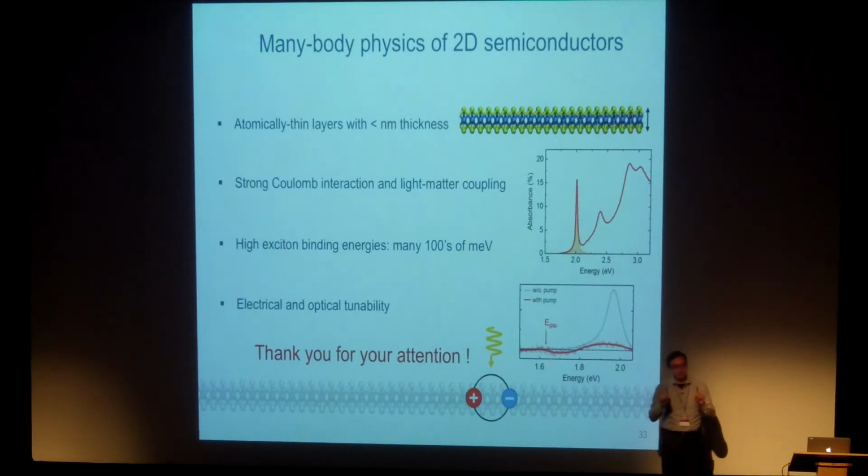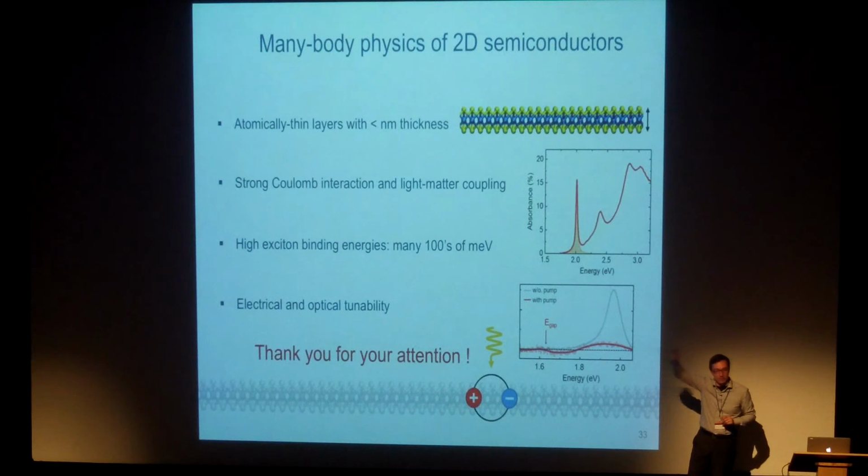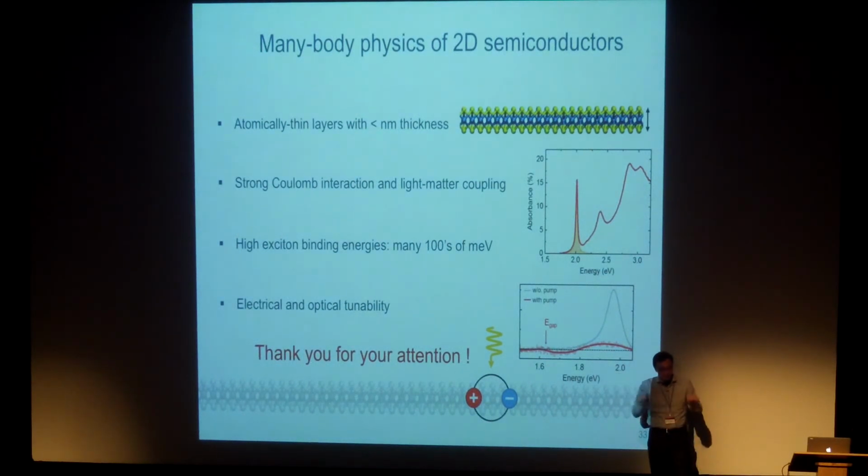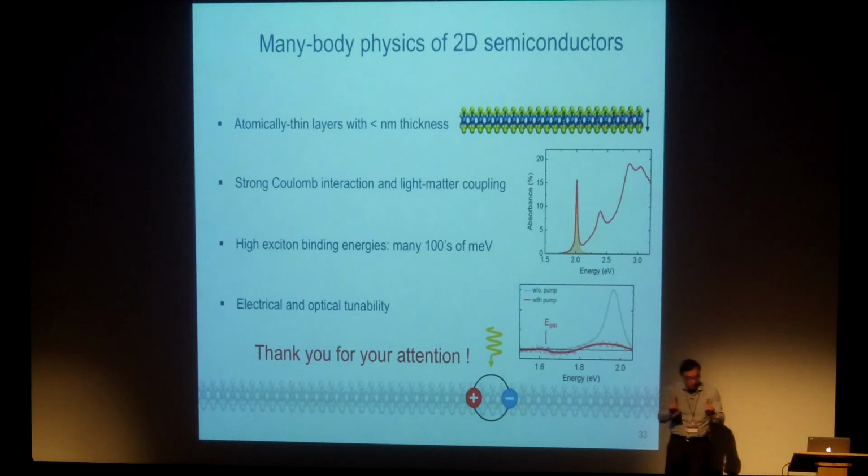As we increase the doping, this difference will increase, and the reason would be that a part of the energy we need, let's say if we think about recombination, we need to put the electron back at the Fermi surface, back at the Fermi energy, and that will give an additional factor. For example, we would see in the optics proportional to the distance of these two states. But the picture is always that the photon can be converted into an exciton, both in absorption and the other way in emission, but the trion forms by taking one of the free charges which are around and binding it. Okay.